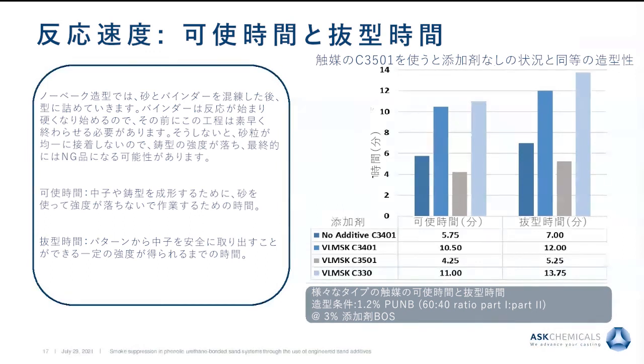Now let's look at the speed of the reaction. So in a PEP SET system or phenolic urethane no-bake, these are two aspects that I think are very important. When you mix your sand with your binder, you're going to have a certain time where you can mix and work with the aggregate, but it's going to start curing, it's going to start hardening. So we have 2 points in time, which is what people define as the work time, and that will be the amount of time available to work with the sand aggregate before it starts hardening.